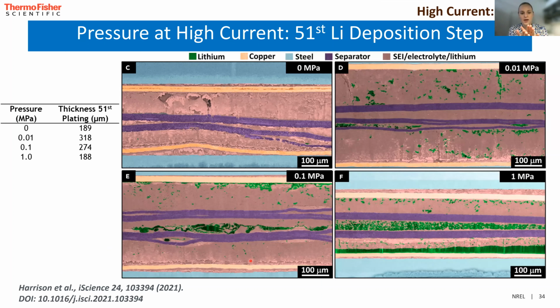Okay, so the way that we looked at pressure using this tool was to cycle the electrodes under a pouch cell, and then to take the pouch cell apart, cut it up, and then to load that into a coin cell, which then we loaded into the cryo stage of the laser plasma FIB and did imaging there. So what you can see here is with pressure, for low pressure at the electrodes, there's almost no lithium left over after 51 cycles.